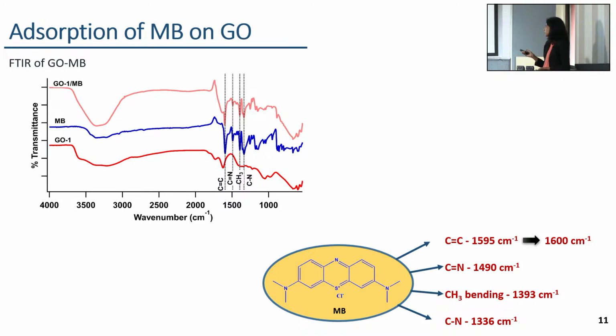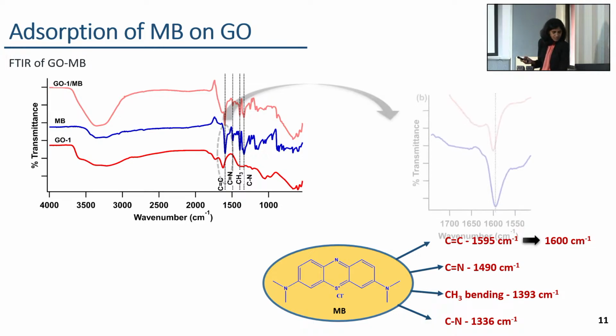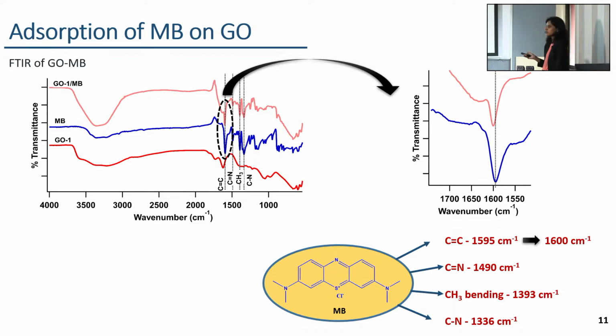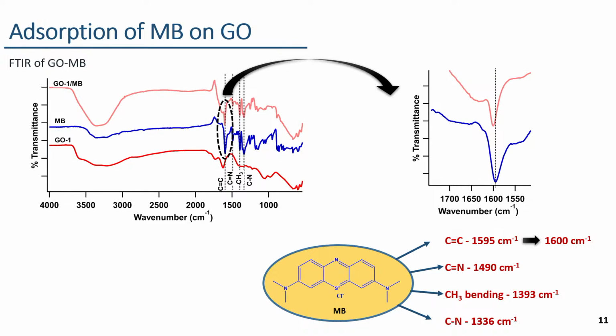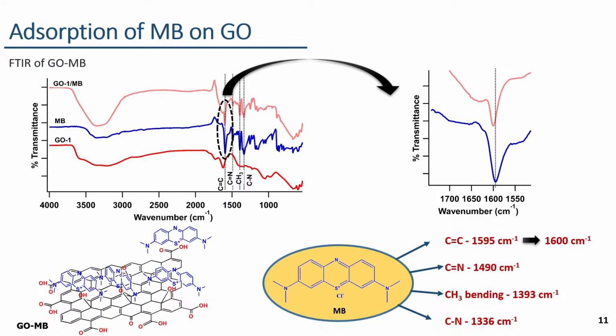So, when comparing these peak positions, we could see that there is a blue shift in the C double bond C of the methylene blue after the adsorption onto graphene oxide. Blue shift means this peak has been shifted to a higher wave number. Most of the literature studies have reported this blue shift with the adsorption of methylene blue onto surfaces in vertical orientations through electrostatic interactions. So, this observed blue shift confirms that the methylene blue is adsorbed onto this graphene oxide in vertical orientation through electrostatic interactions.